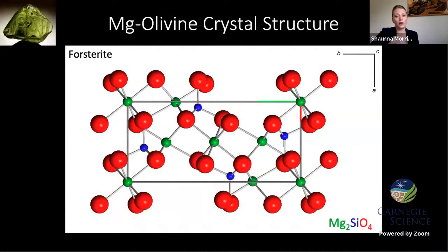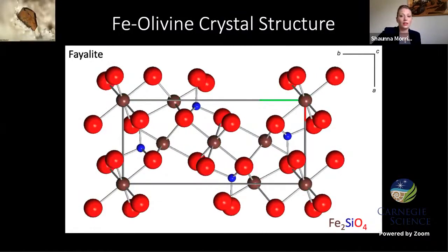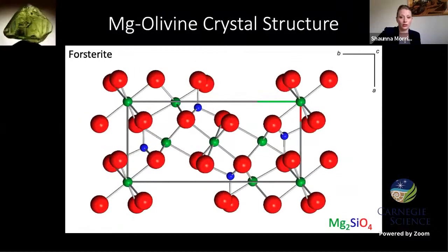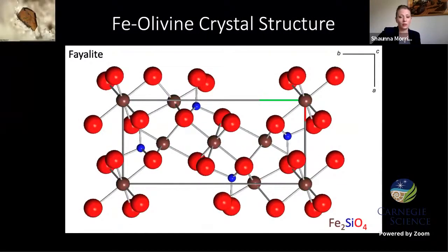Here we have the crystal structure of magnesium olivine. The green atoms are magnesium, the blue are silicon, and the red are oxygen. You can see that the magnesium is pretty small, and when we replace the magnesium atoms with iron atoms in the crystal structure, you can see that the entire structure becomes larger. And it turns out that when you add more and more iron to olivine, the crystal structure size increases in a very regular and systematic way. So by data mining a lot of experimental data from laboratory measurements and using some advanced statistics and data science techniques, we can actually statistically characterize the relationship between the crystal structure size and the amount of iron.